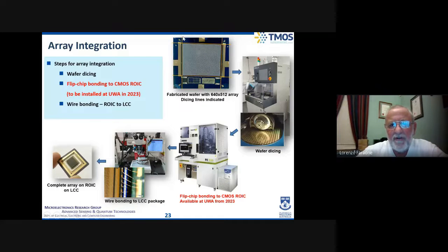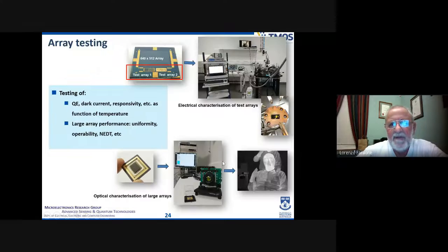Here you cut the detector out using a dicing machine, then flip chip bond it face to face onto a silicon CMOS chip underneath, with the detector array on top. They face each other, and you make 640 by 512 electrical contacts between the indium bumps on the detector array and the indium bumps on the readout circuit. Then you wire bond it to the outside package, ending up with a focal plane array flip chip bonded onto the readout circuit.